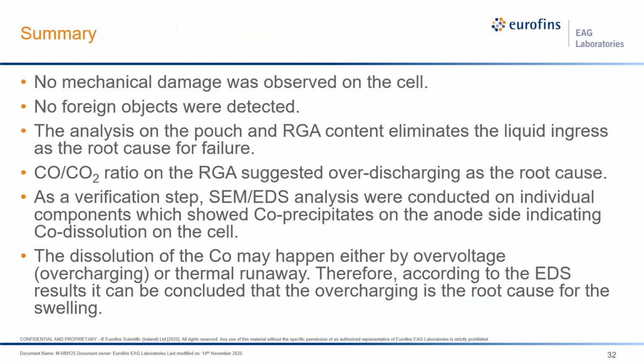So in summary for this case study, there was no mechanical damage or thermal damage to the device. No foreign objects were detected in the 2D X-ray or CT scans. The analysis of the pouch and also the RGA content eliminated moisture ingress as a root cause. But there was a suspicious CO to CO2 ratio, which was directing us towards over-discharging. In order to double check and confirm, we did a full teardown and saw there's cobalt on the anode side, which suggests overcharge was the issue.